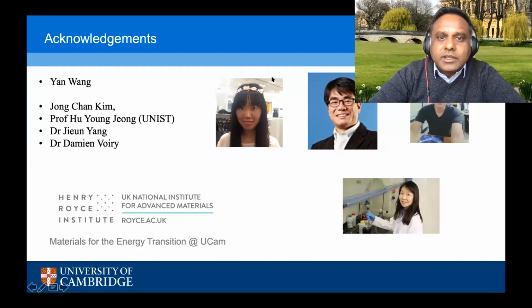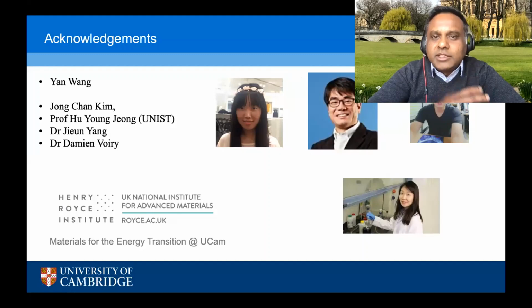How much indium do you deposit? Do all the alloys that you tried result in van der Waals contacts? As I said, we try to minimize the amount of indium. I said 3 nanometers. I think 3 to 10 nanometers is quite normal.